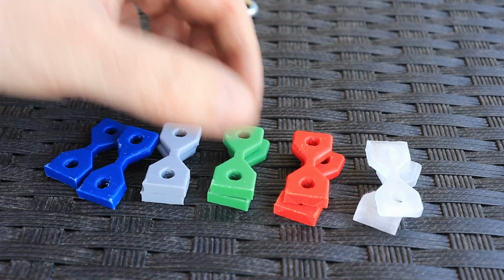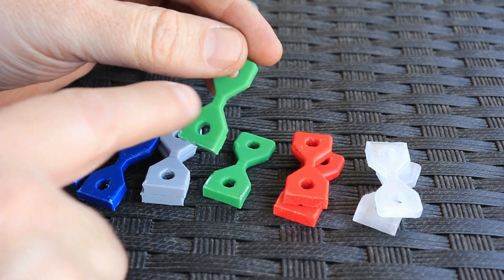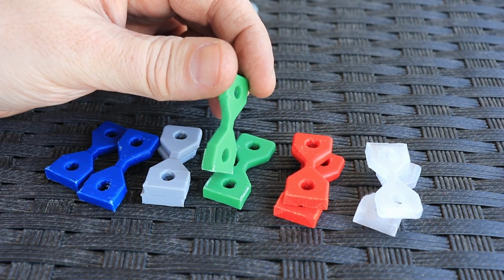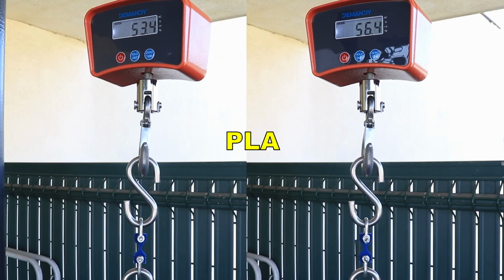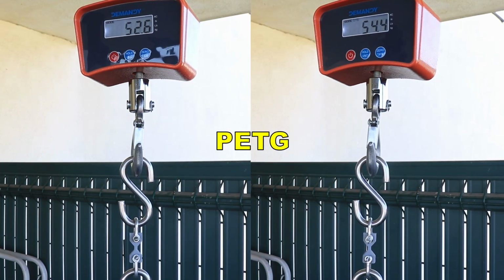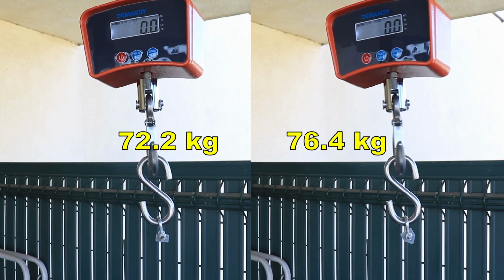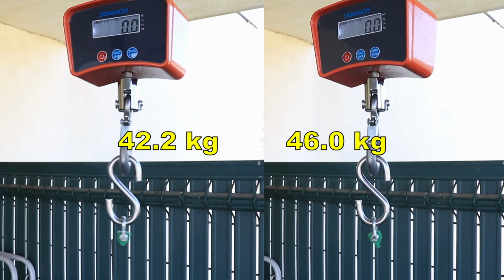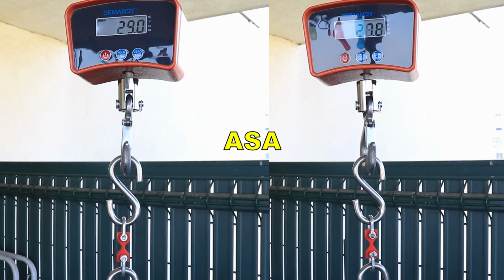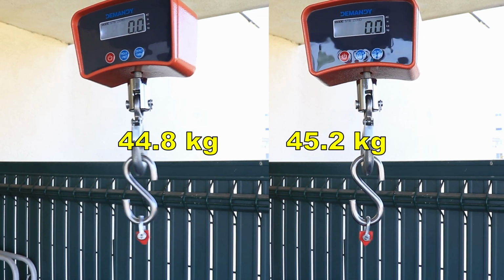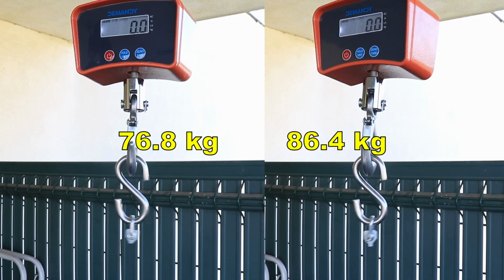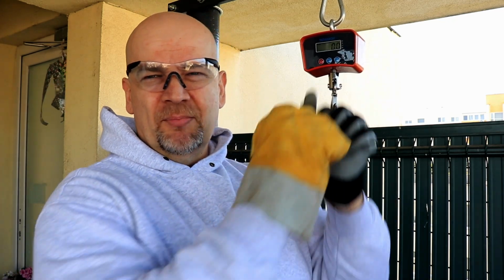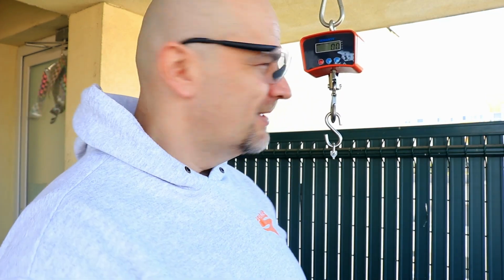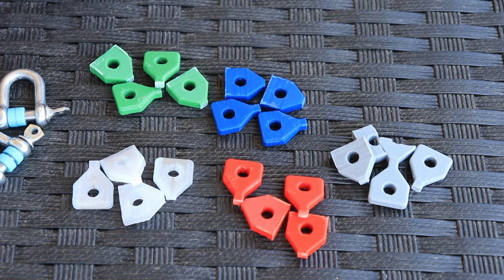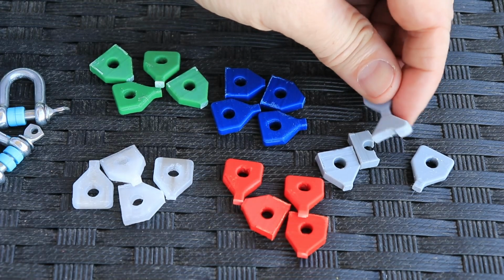And now it's time to check the layer adhesion. These test objects are printed in vertical position, and here the smallest cross-section area is also 4 by 4 millimeters. What is not visible on the footage is that I'm using my own weight to break these test specimens, because I was expecting smaller loads, but I think I should move to the chain hoist here too. After breaking, again I can see that white area on ABS, and only one test specimen didn't break on the smaller cross-section area.